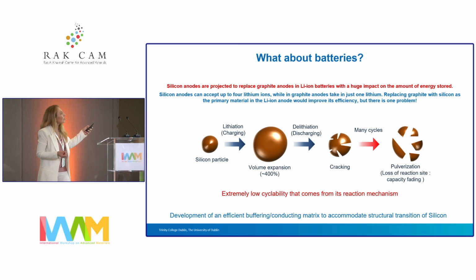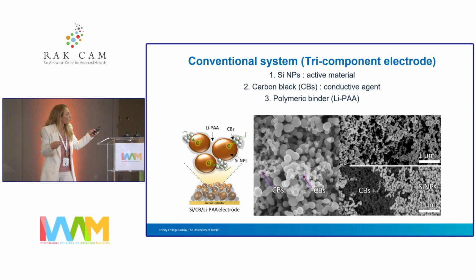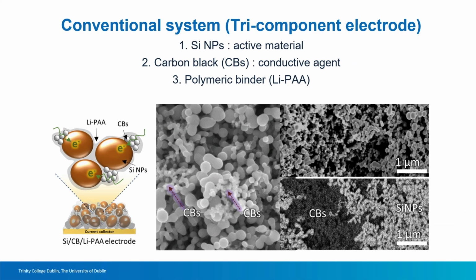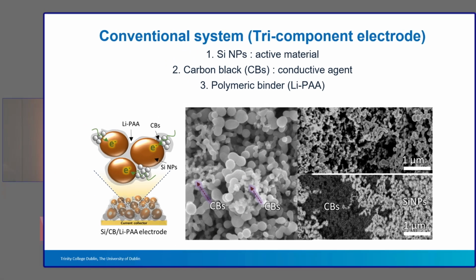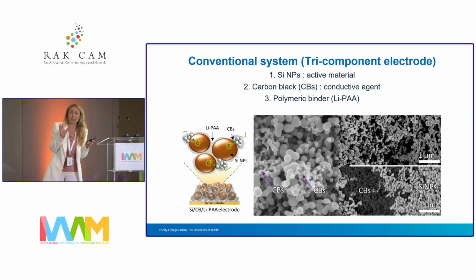So what we decided was, well, let's see if some of our 2D materials can make the trip. The conventional way of improving the mechanical stability of this silicon electrode is quite rough, quite rudimentary. They use the active material, silicon nanoparticles, carbon black to make it conductive, and then a polymeric binder. And the improvement is not really huge. You might go from 10 cycles to probably 50.